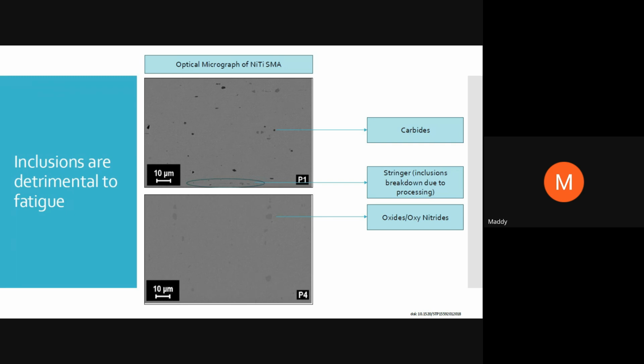And both are bad. You can see when you continue to process the material, because you're starting from an ingot, which is typically either 12-inch or 14-inch, and then you hammer it down, forge it down, and then into billets, and from there you are drawing it into very fine wire. Imagine that wire is going inside your body, wire or tube. So you can imagine the amount of reduction this material undergoes. And so what happens is, these inclusions like oxides and carbides can elongate, they can break up, and they can form what's called stringers.